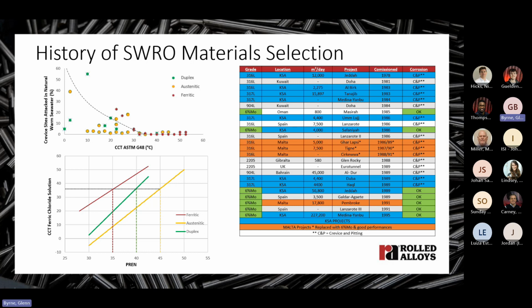So then you can replot this, and you can plot the CCT in ferric chloride against the pitting resistance equivalent number of the ferritic, austenitic, and duplex grades. And the metallurgies of these alloys then begin to differentiate. So you can see, if you draw a line at 35 degrees C in ferric chloride, the implication of that is that you need a PREN of 35 in order to give good crevice corrosion resistance in seawater. Similar for duplex stainless steels, you need a minimum PREN of 40 to get good crevice corrosion resistance in seawater. And for the austenitic grades, you need a PREN of 45, again, to get good crevice corrosion resistance in seawater.